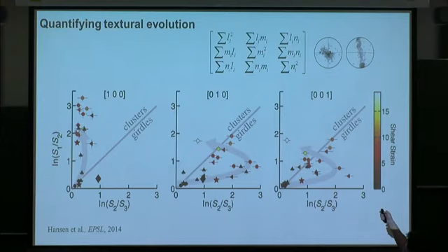So, these are a bunch of individual axes, so these are all vectors, and we can look at a matrix of the direction cosine. This gets called the orientation tensor, and its eigenvalues give you a sense for the shape of this distribution. So here, plotting ratios of those eigenvalues.